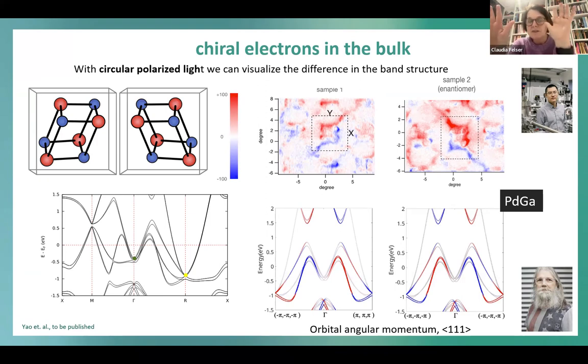So you can now distinguish the band structure. If you use circular dichroism and chiral light, your bands get a phase. And the phase is related to orbital angular momentum. To think more about the orbitals, and this is again going in the direction of chemistry, really at the interface between chemistry and physics, would be maybe something that could shine more light on these interesting chiral solids.